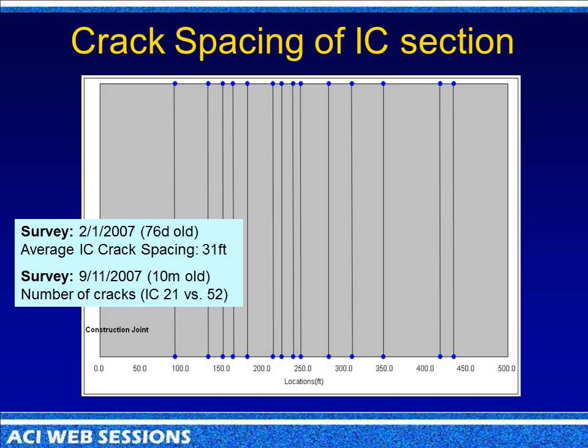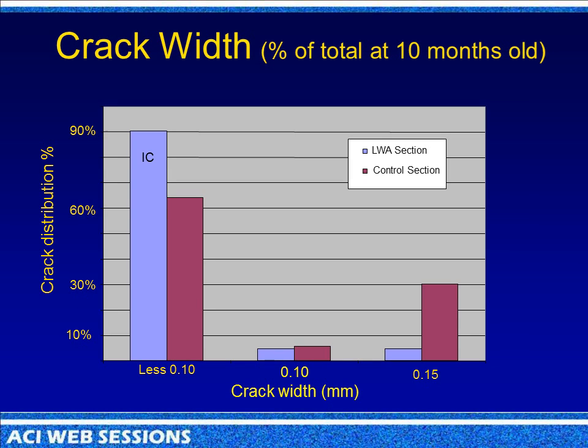And then when they went out again 10 months later, they found 21 cracks in the light internal cured one and 52 cracks in the normal weight one. And here's what they did. Of the 21 cracks, 90% of them were less than this number, and the control had a lot, but look at over here. Of the larger cracks, the control had a much larger percentage of larger cracks.